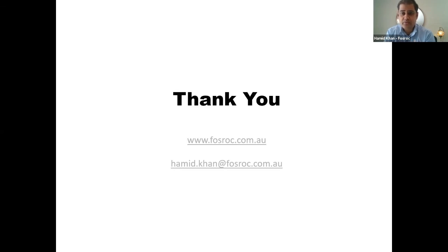So it right away starts from, as I said, saw cutting and all the surface preparation, but the second part is the SSD, which is very important if you are not using an epoxy bonding agent, for example. And then followed by the application, and then post-curing is very important. Specifically for microconcrete, curing is very important, by either a curing compound or by water curing. So these are the points which are good for the quality control.